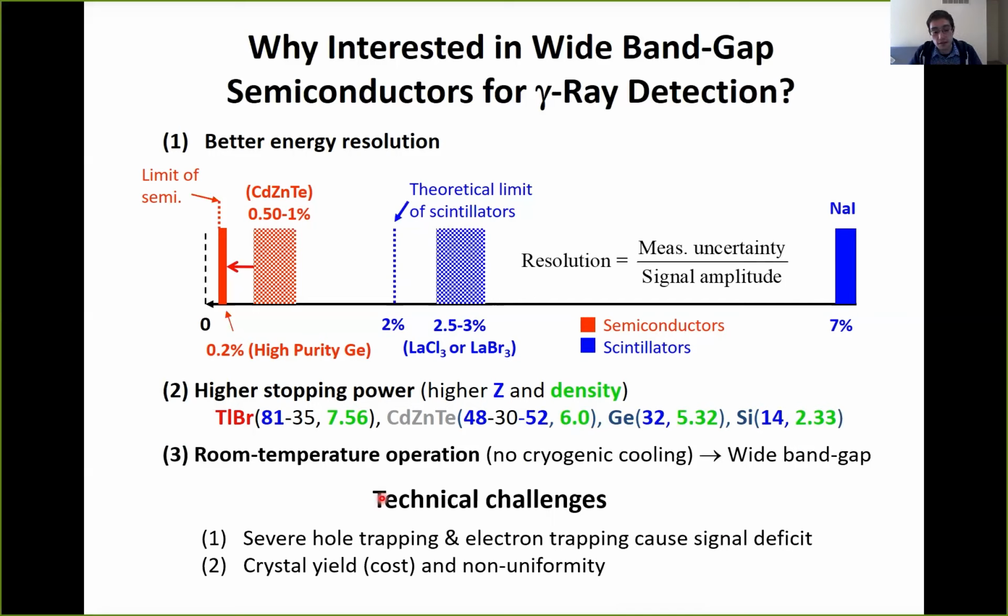Another reason why there's a technical challenge is that these semiconductors are pretty expensive because they have to be extremely purified. The way they're purified is that they basically have a zone refinement. When they grow the boule out, they have a traveling heater that moves the impurities out by melting it and then letting it reform or self-assemble back again, and try to remove those impurities out of the boule.